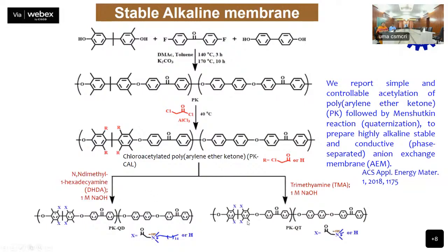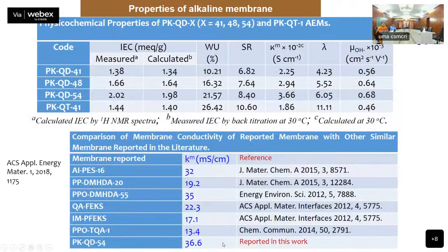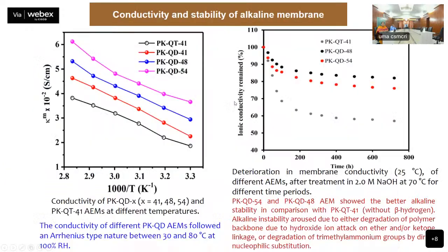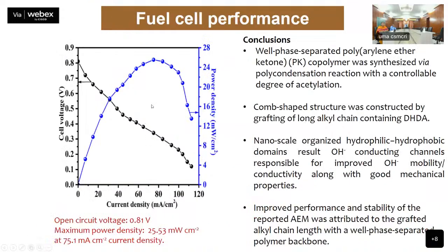So CSMCRI prepared a poly(arylene ether ketone)-based anion exchange membrane for hydroxyl stability. We have varied the amine and studied how the fuel cell performance of the membrane varies. A series of membranes were prepared, and we checked the conductivity also by dipping in molar NaOH at 70 degrees for different time periods, and we have used these in a fuel cell stack.